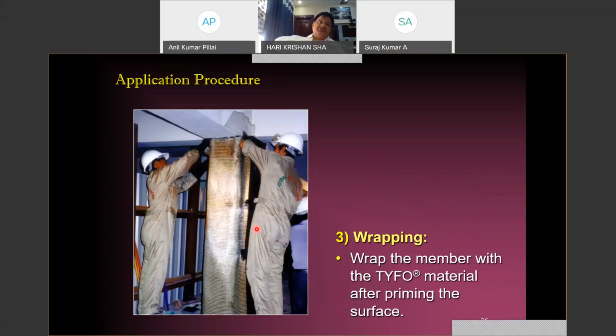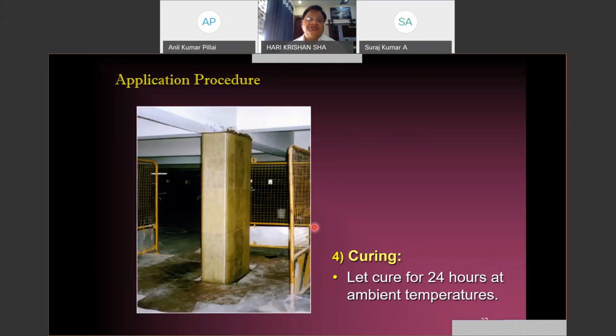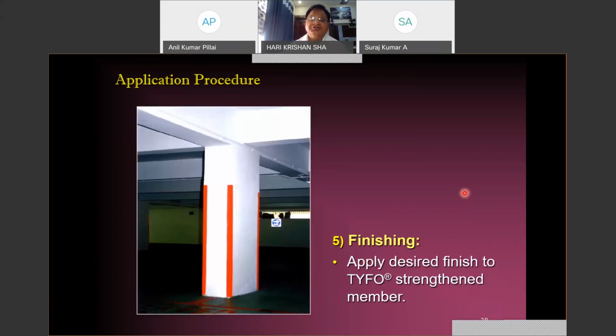This fiber reinforced polymer sheet is available in rolls, so you can simply unroll the sheet, put a layer of the epoxy, and wrap the sheet over the distressed structure. So it is just like a bandage. Once the distressed structure is wrapped, you can leave it for about 24 hours at ambient temperature for curing. So no special kind of curing is done. You simply leave the structure for 24 hours, and after that you can apply any kind of finishing coat and the structure is ready.